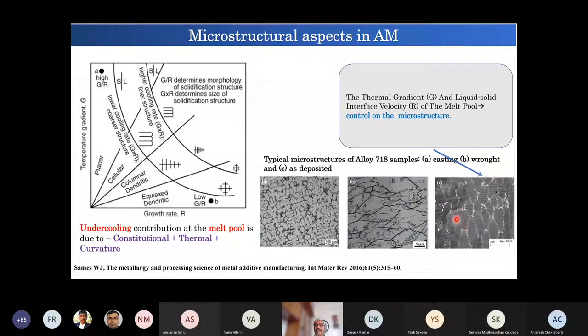And in the additively manufactured case, we get equiaxed grains, which are elongated, but there is always a segregation around this. So the distribution of various alloying elements, at least 5 or 6 important alloying elements, is not the same as in this case or in this case. Another thing that happens is that because of the thermal conditions, it also generates some kind of phases, which may be desirable sometimes and sometimes undesirable. Desirable means, as I mentioned in the beginning, that sometimes additive manufacturing gives a surprise: the properties of additively manufactured products are measured to be superior to the cast and wrought products, which are so well established and whose processes are so controlled. So this happens